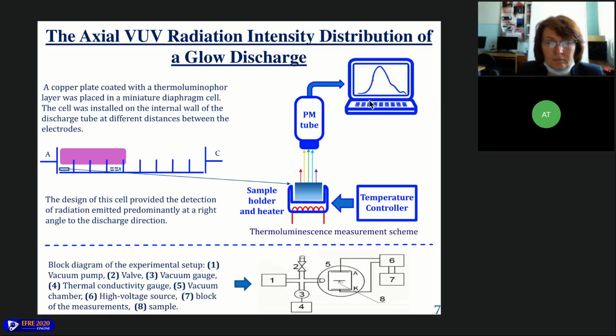Then the sample was placed in another area of the glow discharge. One of them was here, then another was placed here, and so on. This procedure continues until we get all the thermoluminescence curves from each area of the discharge. It's worth noting that the intensity of vacuum ultraviolet radiation of glow discharge highly depends on voltage between electrodes and pressure in the chamber. So we did experiments depending on these parameters.